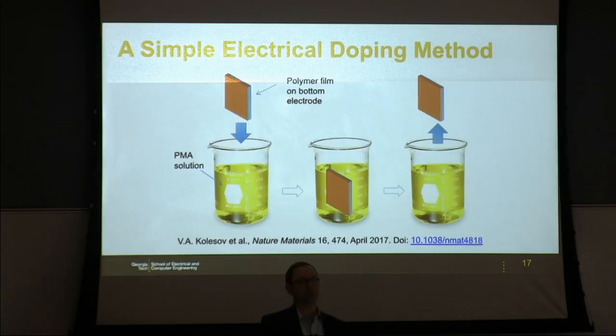Now, the way this is done is either through ion implantation, or you can heat up the material to about 1,000 degrees for an hour, and then you have these dopant materials that diffuse into the silicon and do the doping for you. So it's a very energy-intensive process. Here, what we've discovered with these organic semiconductors is that you can take a film that you first deposit on your substrate, and then you dip it into an oxidizing solution of phosphomolybdic acid, or PMA, providing that you have the right solvent, because it's a process which we believe is mediated by the solvent and also some hydrogen. I don't have time to go into details here. But all it takes is you take that film, you dip it in a liquid for a few seconds at room temperature, you take it out, you clean it, you're done. Okay? And that works actually like a charm.